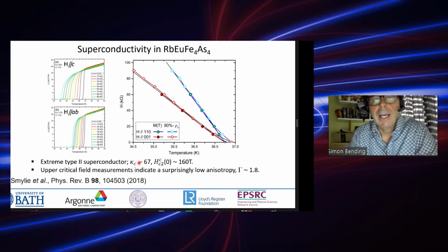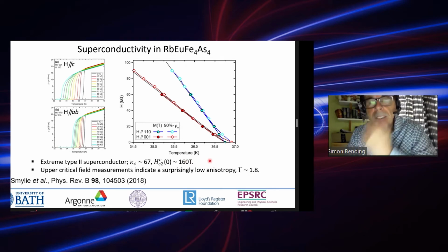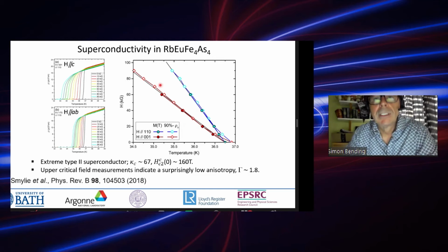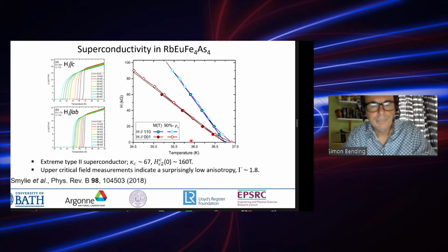For example, along the c-axis, kappa C is something of the order of 67. HC2 at zero temperature is very large, something like 160 Teslas. And these numbers, in fact, are even larger in the in-plane direction, the AB plane direction. Looking then at these upper critical field measurements, although, of course, the fields are higher in the AB plane than along the c-axis, in fact, the anisotropy is relatively low and is only about 1.8 in this crystal itself. So it's not a particularly anisotropic material.